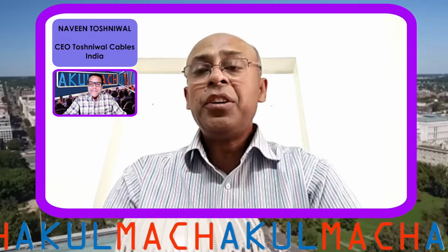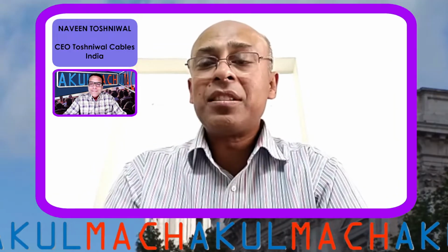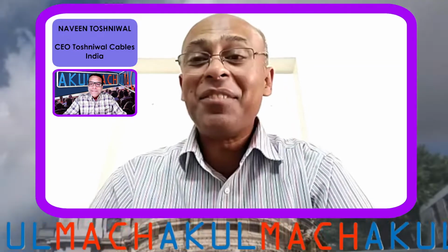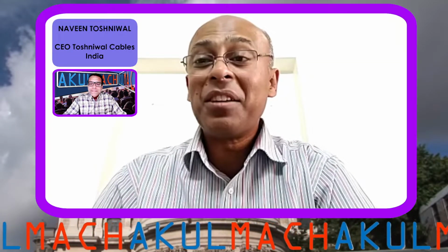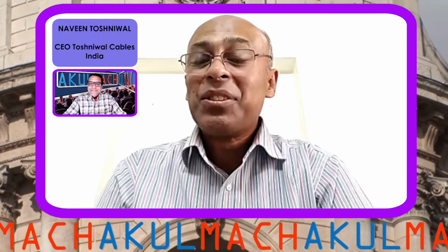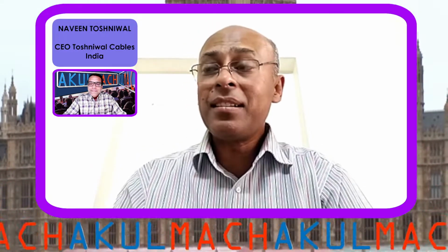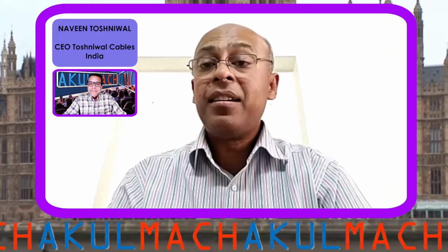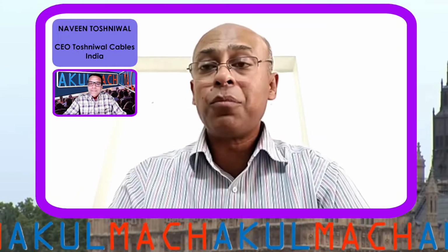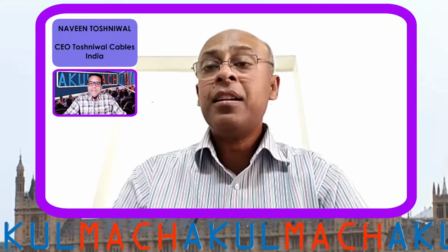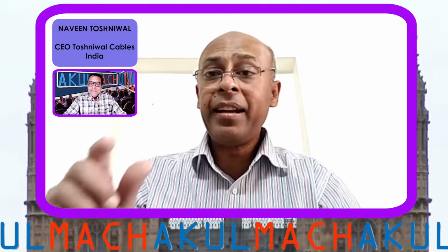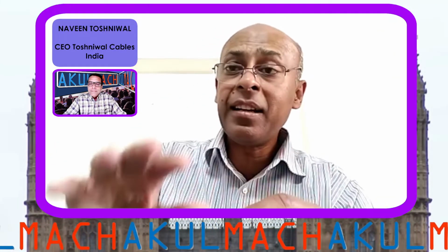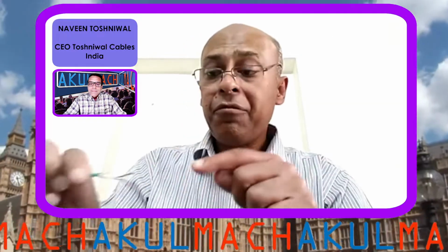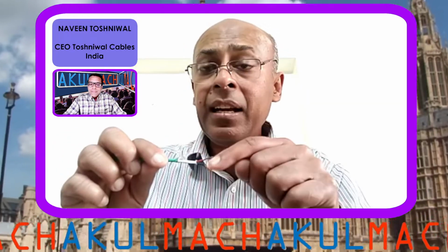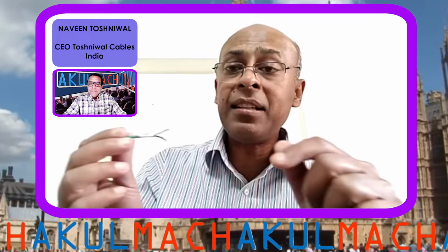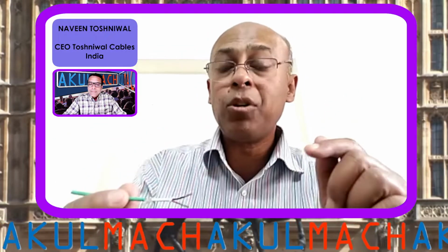Actually, you are absolutely right, because you told me last time you were a physics student, so you already have quite a bit of knowledge on this. What is the most interesting part is that this Teflon is not extrudable, remember. Teflon PTFE, polytetrafluoroethylene, is not extrudable. So what we have to do is make it in tape forms, slit it in tape forms, and then we wind through a taping machine. And after the winding, we pass it through a sintering oven.